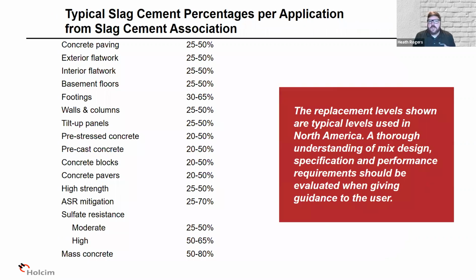So how's it used in concrete? The Slag Cement Association put out a chart basically showing how much in certain types of mixes is typical usage. So the main thing I would like you to take away from this is slag cement is flexible. It's not a one-size-fits-all approach to different concrete mixes. It can be adjusted depending on the properties that you're seeking. So you can go with a smaller amount for concrete paving or a much higher amount for like mass concrete, depending on the properties that you're looking for.